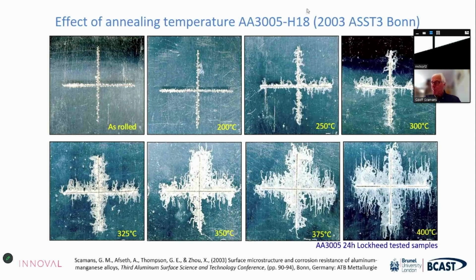What we were able to show was that it was very much controlled by the presence of deformed surface layers. You can see how quickly filiform can grow on a suitable surface. There's no cleaning or pre-treatment. These are just ground surfaces or rolled surfaces that have just been lacquered and then scribed and then exposed to a saline-containing environment. And you can see how quickly, depending on the annealing condition, the filiform corrosion filaments develop. Of course, this is not nice if you're worrying about filiform resistance of a painted surface.